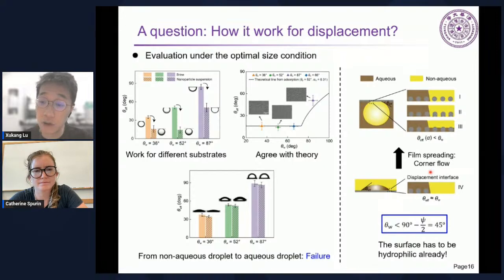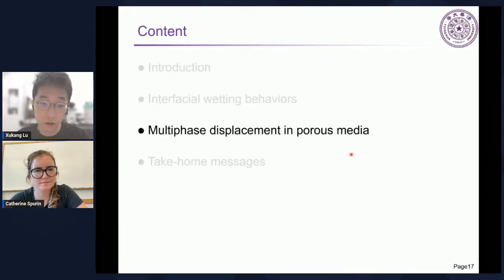And for channel flow, we always have this corner flow when the surface is hydrophilic enough. For a rectangular channel, we have this 45-degree criterion. That means the surface has to be hydrophilic already to promote this pre-existing film spreading so that nanoparticles can play their roles. And this is basically a hypothesis extracted from all these observations and analyses, and we will then validate it in porous media experiments.